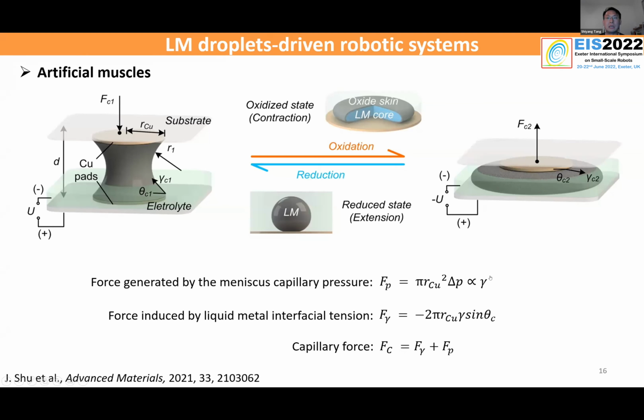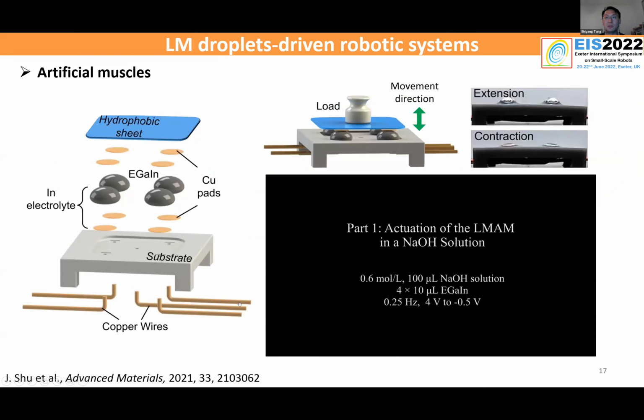By controlling the interfacial tension, we found that we are able to induce contraction and extension of the liquid metal bridge, thereby making a kind of liquid-based artificial muscle. I think it's better to use the footage to show the concept, but instead of using one droplet here, we use numerous, like 4 droplets, to drive some loads.